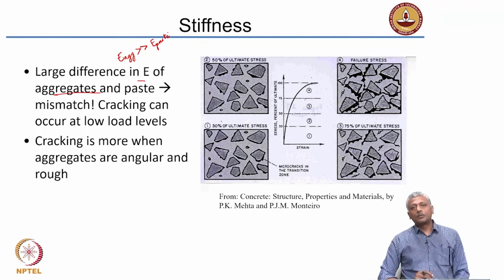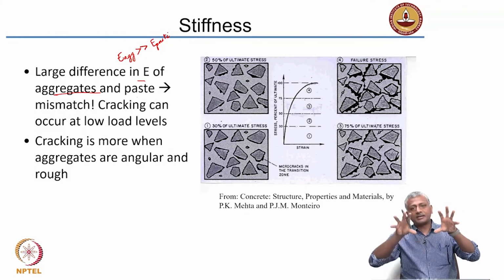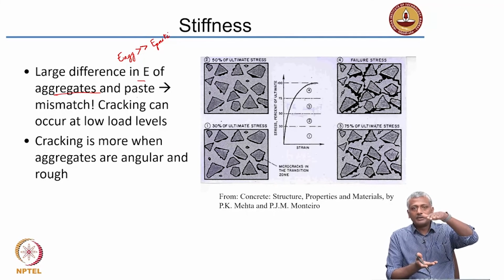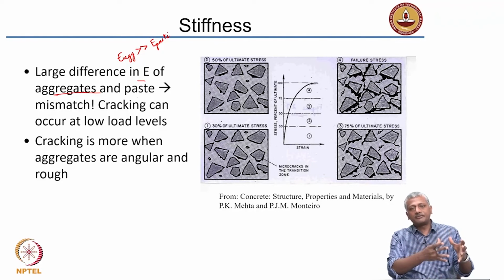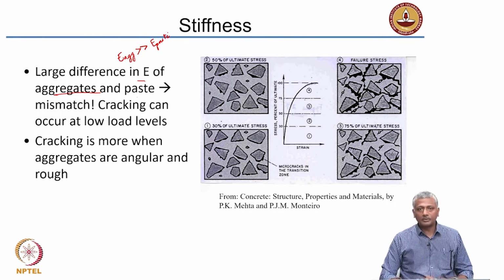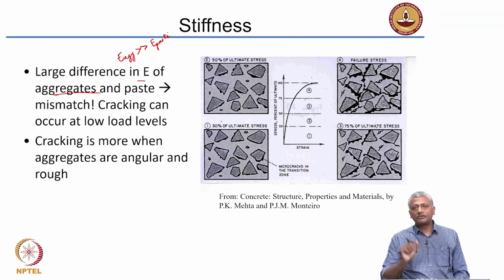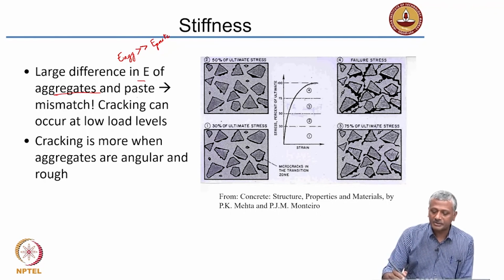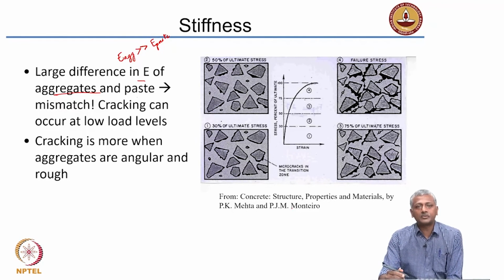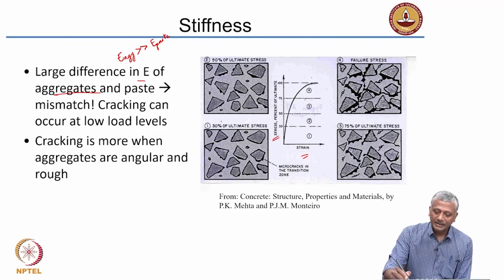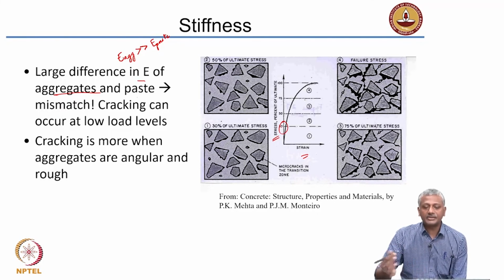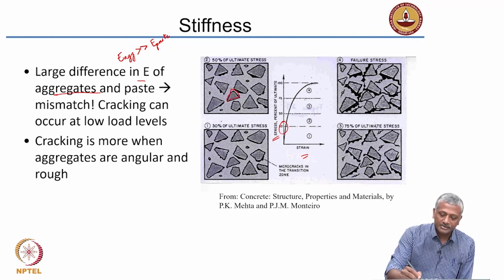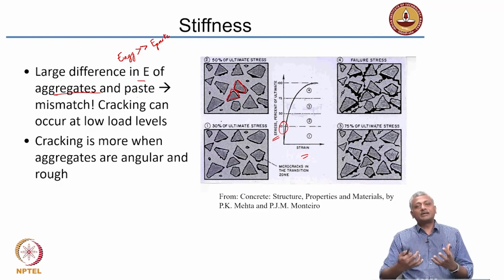So, what will happen now is, when there is a large mismatch, where one stiff material is there and another less stiff material is there, when you start loading this, the load distribution will be such that the stiffer phase will get more load. The aggregates will attract more load. So, the zone of paste which is attached to the aggregate will be experiencing very high stress levels as compared to the zone of paste which is away from the aggregate. So, at very low load levels itself, here for example, this is a standard picture you see in many textbooks on concrete. If you plot the stress versus strain, even for stresses which are less than 30% of the breaking stress, you will start seeing that there are failures of the paste around the aggregate, because the aggregate has attracted more load there.